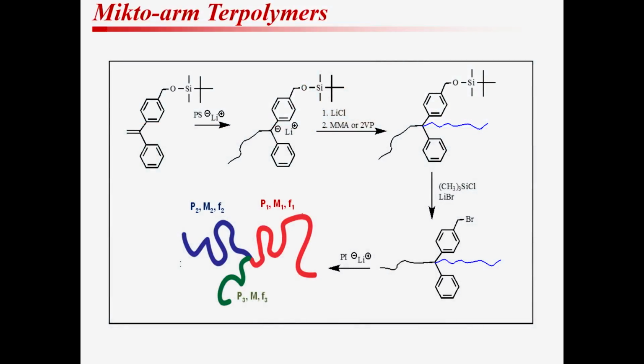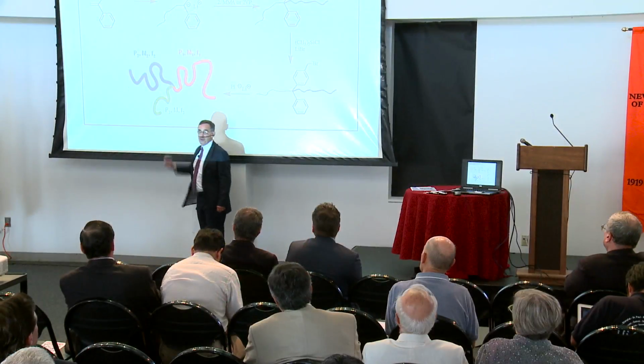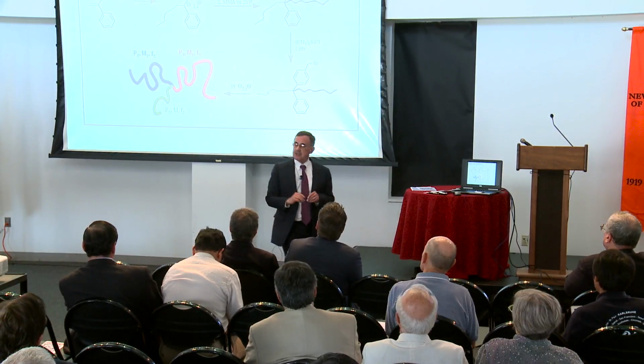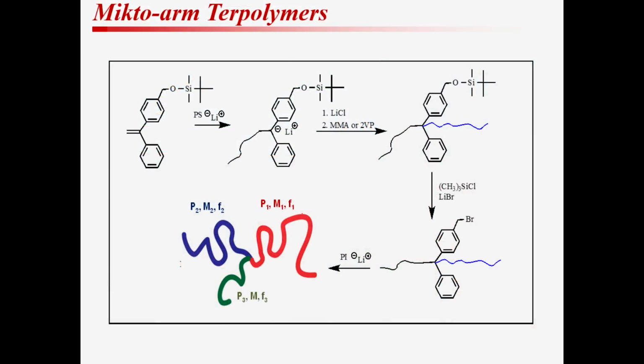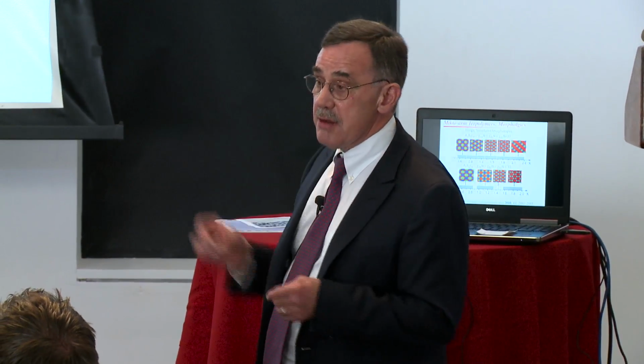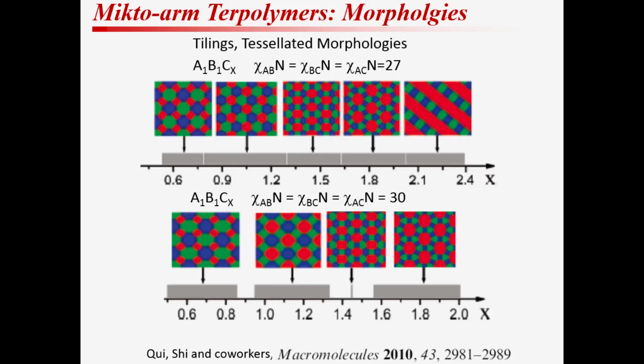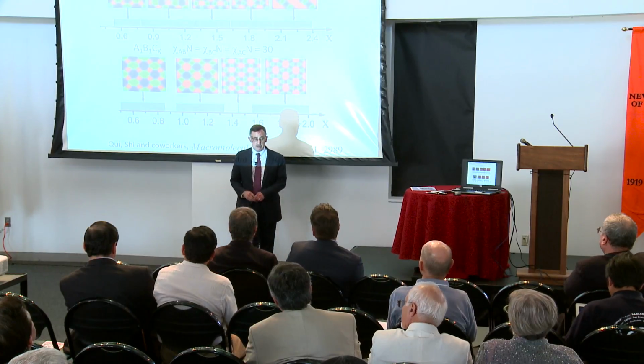And we haven't done this yet, but I'm going to show you what we are doing, is that we're using basically a molecular architecture. And here, rather than take a simple diblock copolymer, we're taking a triblock copolymer where all of these are connected at one point, and that's called a miktoarm polymer. What's very interesting about these molecules is that they form a tiled type of structure. Now, I know many of you have tiled your patios or have tiled your bathrooms, etc. You can't place these tiles down arbitrarily, and in fact, you have to place these down in a very well-defined way. And these are theoretically what you would see for these miktoarm polymers, where you have these morphologies where you have domain 1, which is red, domain 2, which is blue, and domain 3, which is green.